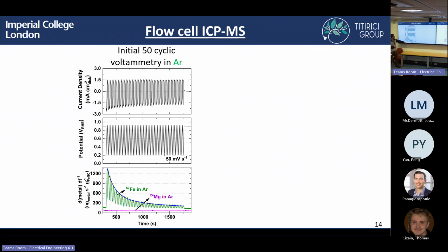So we can see, looking at the magnesium, which we use as a template in the material, that this doesn't seem to be varying at all as we change the potential. And so we didn't really focus on this any further. Instead, we just look at the iron, and we can see that over the first 50 cycles, we see this exponential decay in the iron dissolution. It seems to stabilize once we've hit around 50 CVs. So we can see that during this time, we seem to be cleansing the catalyst of some very unstable iron species.